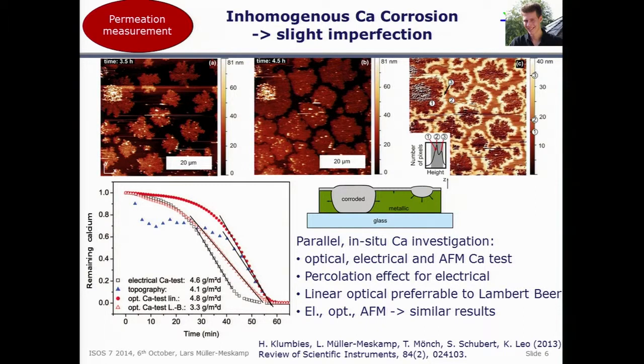Okay, so this slope is very important, and one of our students, Hannes, he worried a lot that it might not be real linear for calcium layers, and actually he found that when you look with the AFM on the surface of your calcium, it does not degrade homogeneously, but it degrades, it forms spots. There's a nucleation, and then the calcium hydroxide grows around it. So if you have a differential AFM, you see these islands are growing. So something is corroding to the bottom. There's a thin film around 60 nanometers and then getting wider.